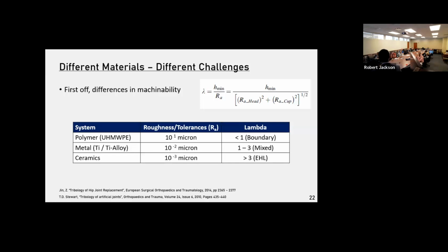What's important to note about these three whole regimes of materials is that they do have different roughnesses or tolerances that you can machine them to. Polymers are typically cheaper or easier to manipulate because they're softer, but your roughness is going to be on the 1 to 10 micron level. So you're probably going to be operating in boundary lubrication conditions. That's a pretty aggressive environment for a soft material. You can have a lot of wear, even though you've got this really slippery, cohesive polymer system. It can break down, form a lot of wear particles, and cause issues. So there are problems with the magic polymer that some of these sci-fi shows use.